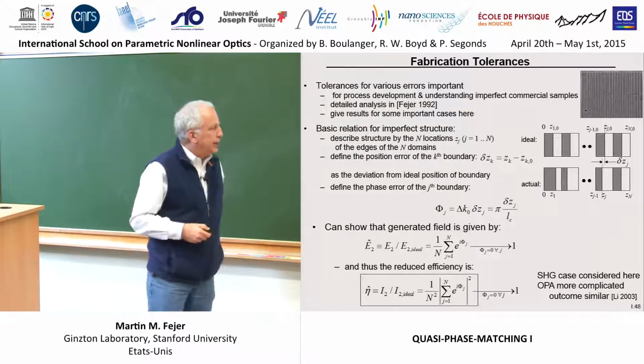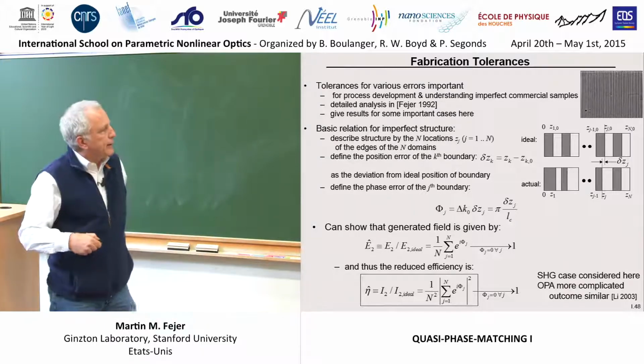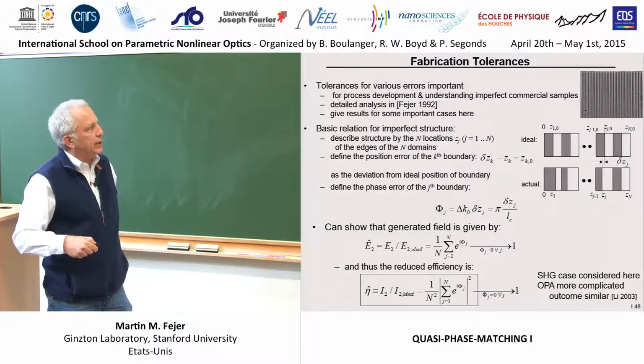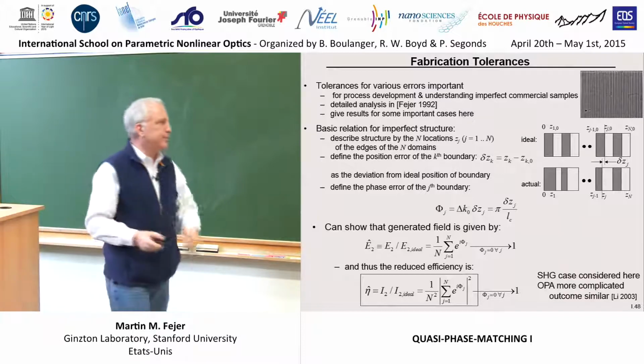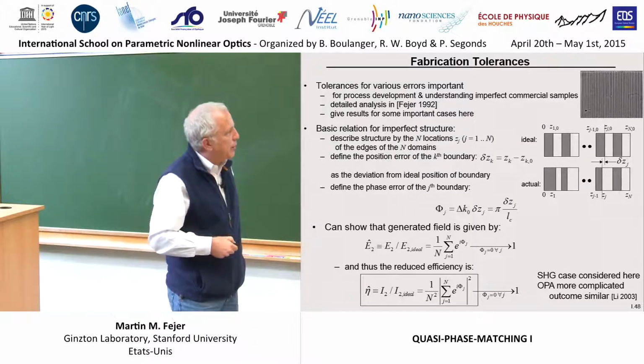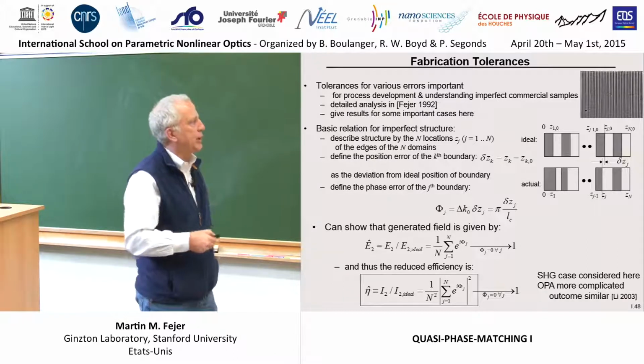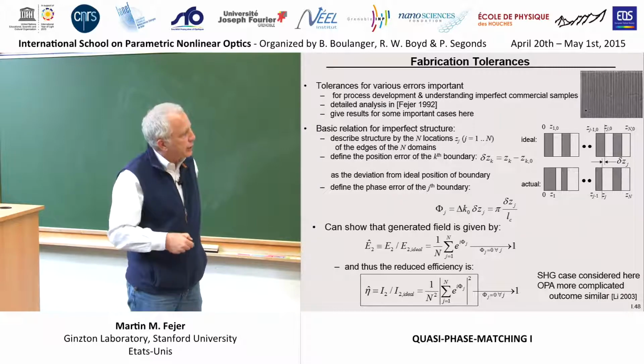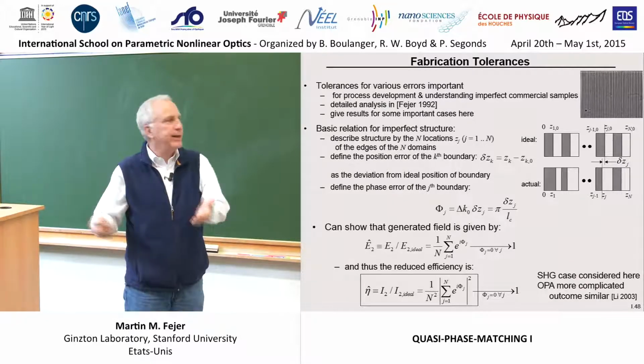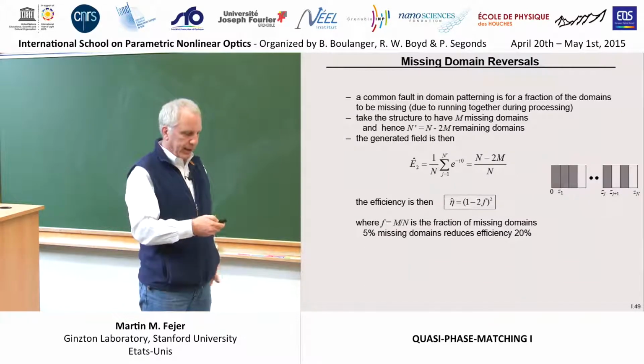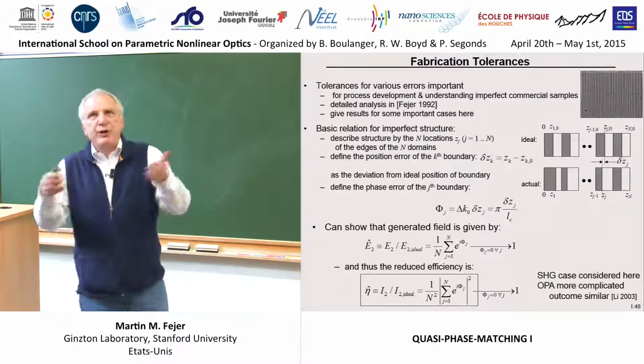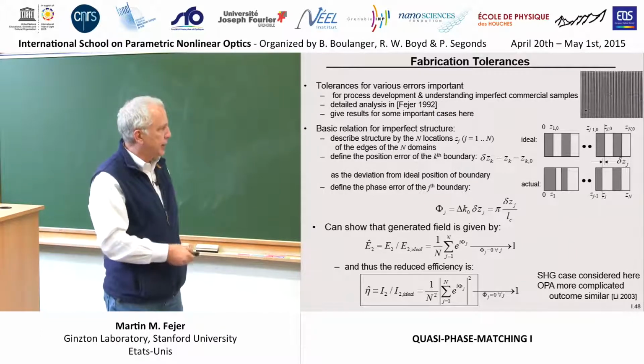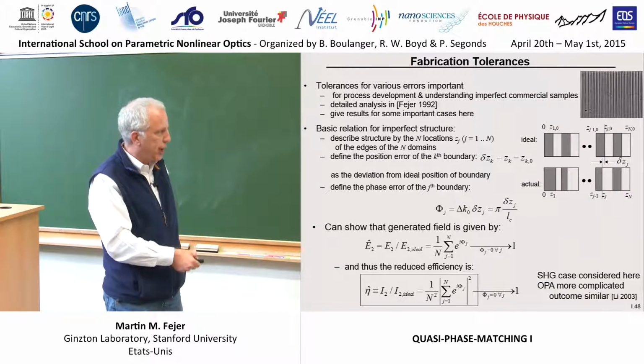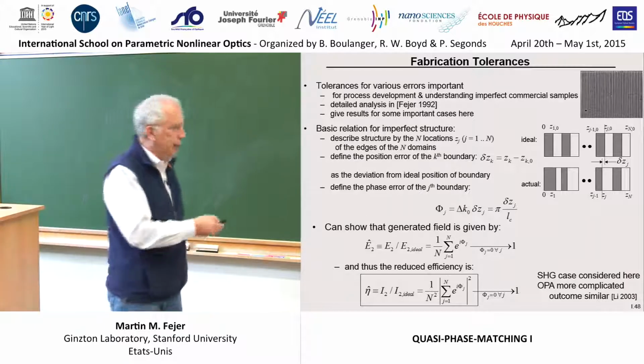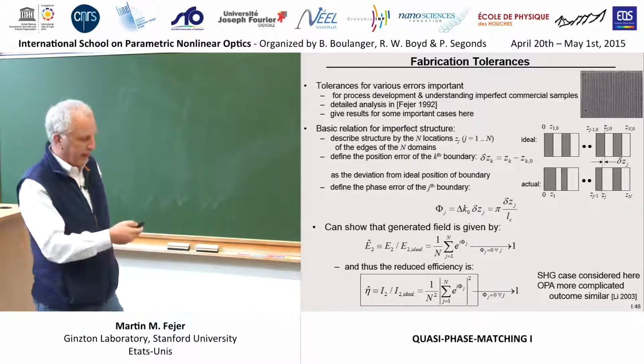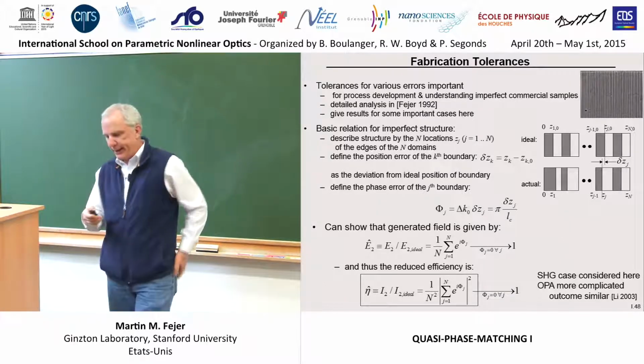So you can show, and it's again in that 1992 paper, that the ratio of the actual generated field in such a structure with errors compared to an ideal field goes like the sum over all the domains of these position errors. So if all of them vanish, each of these terms is 1. You sum from 1 to n. You have n divided by n. A perfect structure, this is just 1. And the reduced efficiency goes like the square magnitude of this thing. And so, of course, it just will also approach 1 as you have a perfect structure. So the question is, what happens if you have an imperfect structure? And you have to evaluate this sum for some real errors.